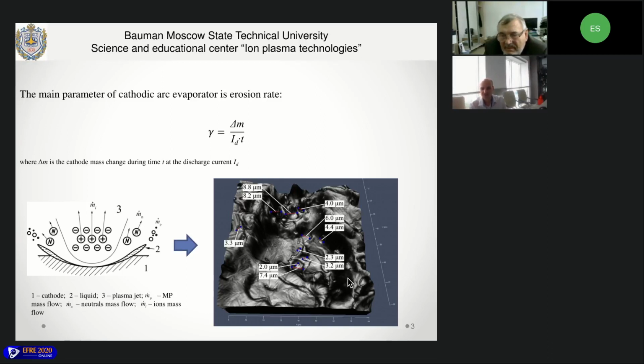So here you can see the cathode crater, and the cathode craters have a diameter of about 70 micrometers for titanium. This crater consists of a large number of little craters with a diameter from 2 to 10 micrometers. And from this area, the ions and microparticles go towards the vacuum volume.